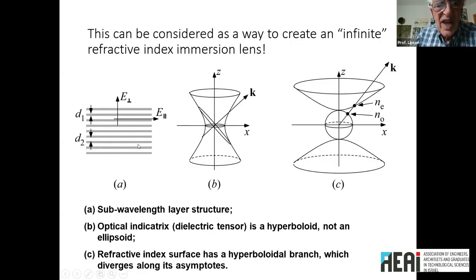Now, there are two refractive indices. The two epsilons for this material depend on the polarization. If the polarization is normal to the layers, then as we know, it's D which is continuous at the interfaces, and therefore you get one of the refractive indices. If you go the other direction, if the field E is parallel to the layers, then it's E which is continuous, going from one to the other. This is D, this is E.